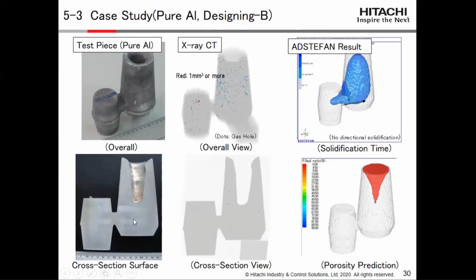It shows the real object, and the result by X-ray CT scanner, and the ADSTEFAN result shows that the porosity area is only in the riser. In the product, it is not happening. And it is also not directional solidification.